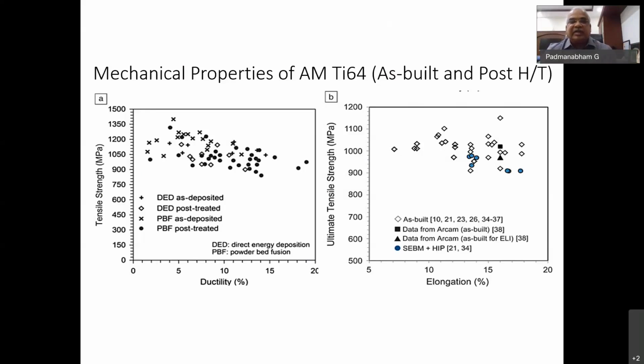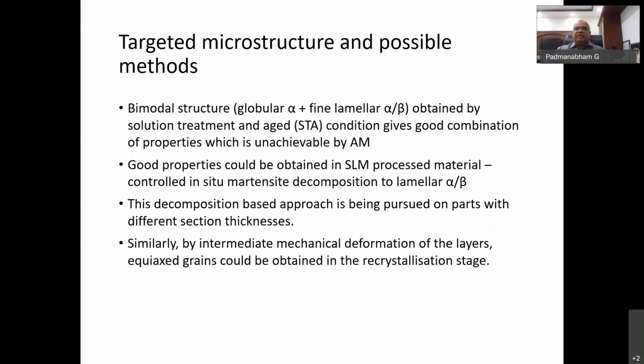with better properties. So when you talk of titanium 6 aluminum 4V material, we always look for a bimodal structure like globular alpha plus fine lamellar obtained by the solution treatment and aged condition. It gives the right combination of properties like specific strength and toughness and fatigue behavior we are looking for, which is unachievable by AM, but good properties could be achieved if we can do in situ martensite decomposition to lamellar alpha beta. So this is too much getting into the molecular level or phase level transformations that we are looking for. This is a subject for a 1 hour talk. I would not like to go too much into it. So by intermediate mechanical deformation also people are able to achieve the properties that they are looking for.